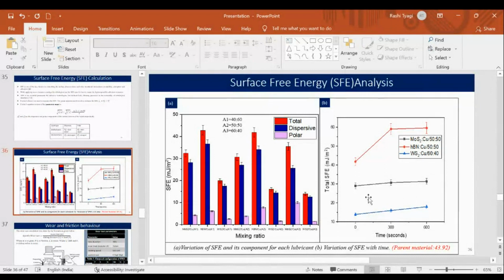Also, these mainly remain stable with time. Sometimes a little increase in these values of surface free energy takes place, because adhesion forces become high with increase in time. So surface free energy increases with time. At low adhesion forces, there is a low surface free energy that will provide higher resistance. So these are the surface free energy values that we have obtained.